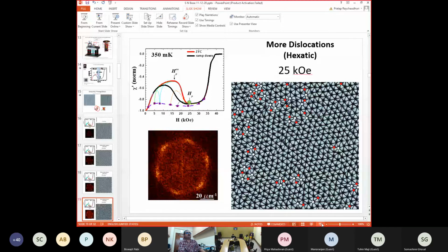So here the Bragg spots are really very broad, but you can still see the 6-fold orientation, and in the field of view, you see only dislocation. There is no disclination. If you look carefully, every red has a nearest neighbor of white. So sometimes you have this red, white, but you don't have any red which is isolated. But then you cross this HP,